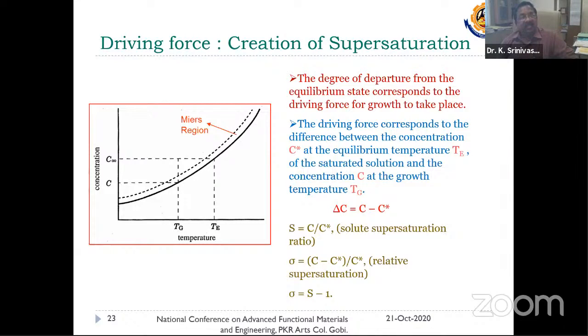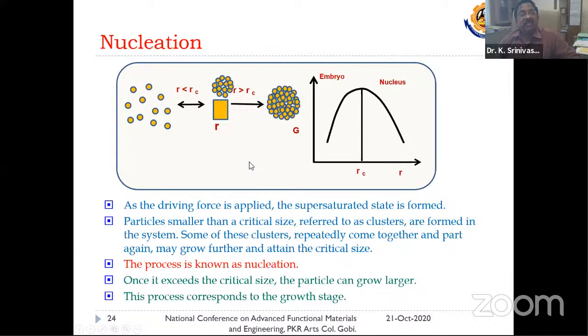When you go on increasing the concentration in the solution, the radius of the cluster will increase further and further, and at one stage it will attain a critical radius. Till it reaches the critical size, there are chances of disintegration of the cluster of molecules as well. So both disintegration and integration are possible, 50-50, before attaining the critical radius of the nucleation cluster. But once it is achieved, there is no chance for disintegration; there is only the chance for further growth.